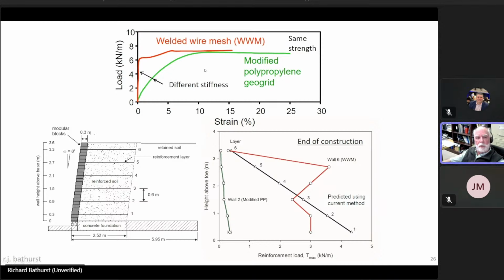So here at the top, you see a segment of that previous slide. You can see the stiffer welded wire material compared to the geogrid. Here again, as a reminder, is the cross section of these two walls. And here are the results. The symbols that you see here are the loads that were recorded in the 6 different reinforcement layers in the polypropylene wall. And here the red curve is for the nominally identical wall, but with the stiffer metallic reinforcement.